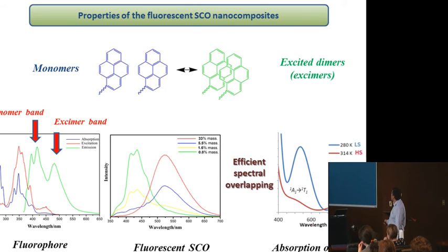We can see that we have a good overlap between the emission of the dimers and the absorption of the spin crossover complexes again. And here we report the composite materials as a function of the percentage of fluorophore. Of course, when you have a small quantity of fluorophore, you favor the formation of monomers, in green here. So here is the emission of the monomer. You have no dimers. And when you increase the quantity of fluorophore, you favor the formation of dimers. So for the red, you have mainly fluorescence of dimers.